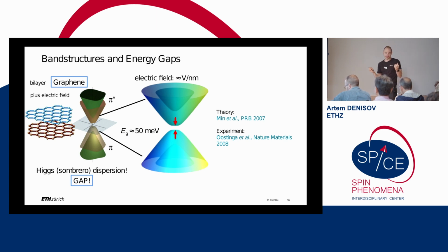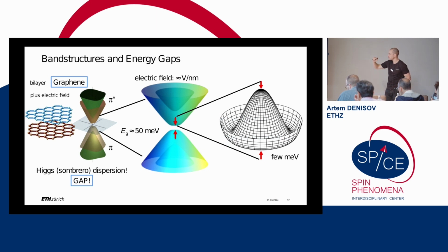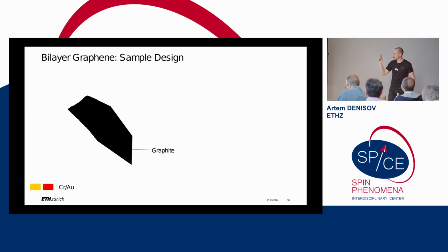And this way, as experimentalists, you're really limited by how good your insulator is. The size of the gap is tens of millielectron volts. It can go up to 100 or 120 millielectron volts. So it's enough. Nowadays there was huge progress in the last 5 years, and I will show why. But this is enough to get a really good quality material to host spin qubits. All right. Also, the spectrum has a funny shape like this. It's a Higgs potential. It also has some non-trivial topological properties, but I'm not going to talk about them much because I'm an experimentalist and work with observable quantities.